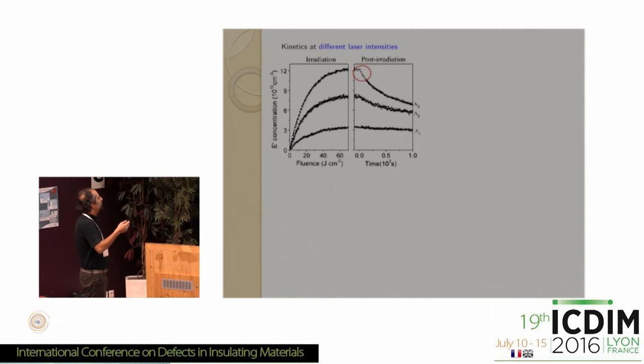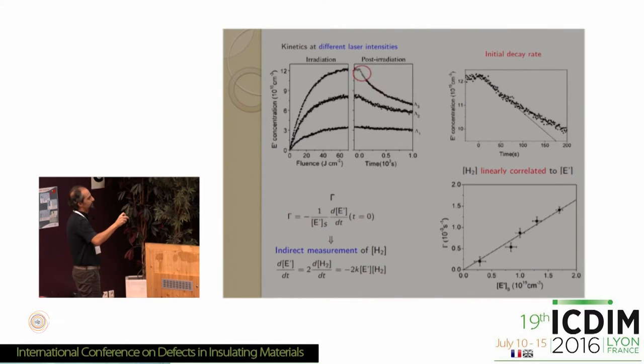One way to be convinced of this is the following. If you study the decay rate of the silicon dangling bonds as a function, for instance, of laser intensity, so these are kinetics obtained at different laser intensities. Defects always get generated, but they get to different concentrations, and then they decay with different rates. So from this initial decay rate, extracted from this part of the kinetics, it's possible to indirectly estimate the concentration of hydrogen responsible for the decay by doing some math.